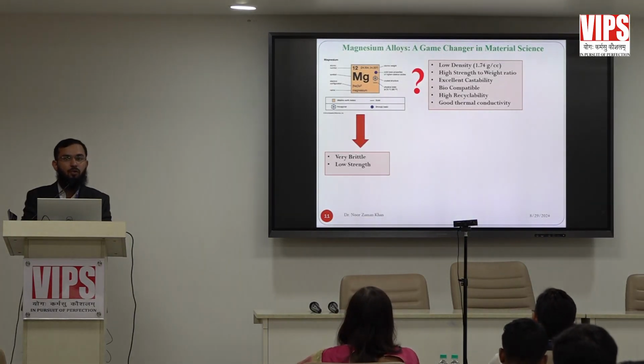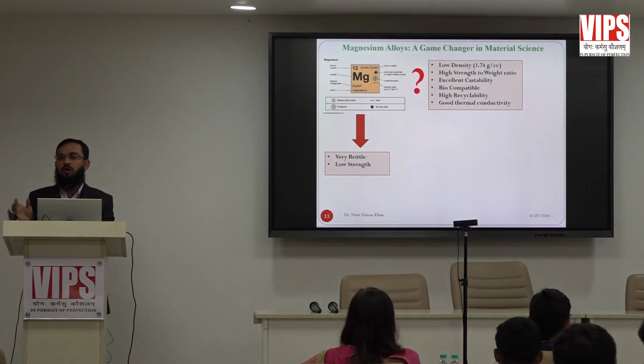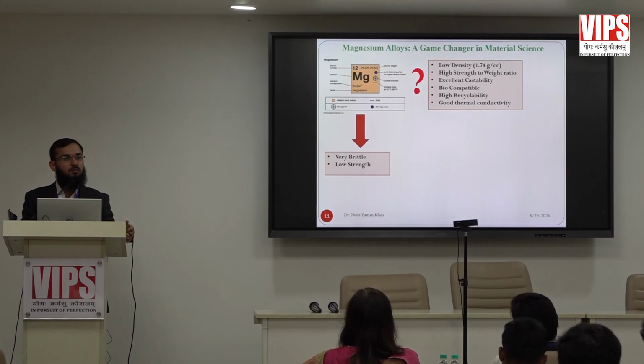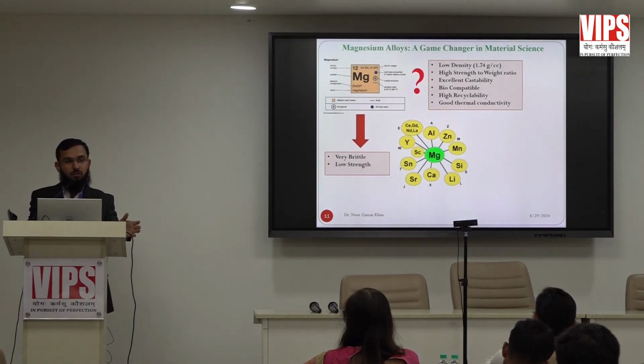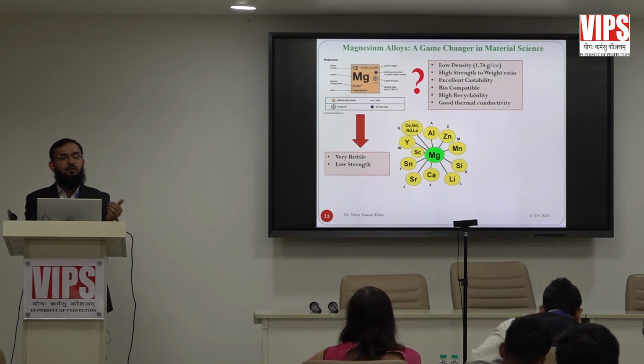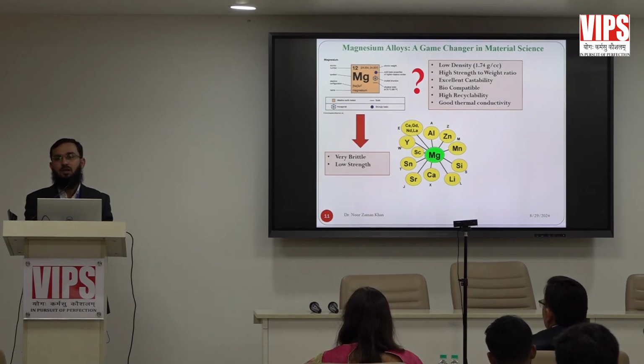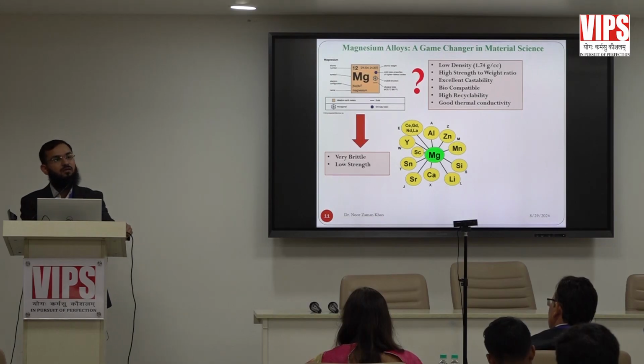Now the problem with magnesium and magnesium alloys is that they are very brittle and have low strength. Pure magnesium, I'm talking about pure magnesium, is very brittle and low strength. If a material is brittle, we cannot deform it. It won't deform, it will break. If it has low strength, we cannot use it for automobiles because we don't need to compromise the passenger safety. So what could be the possible solution? Solution could be alloying. We can go for alloying various elements: aluminum, zinc, silicon, manganese, other rare earth materials, cerium, yttrium, etc., in order to improve the strength as well as the ductility. This could be one of the possible solutions.